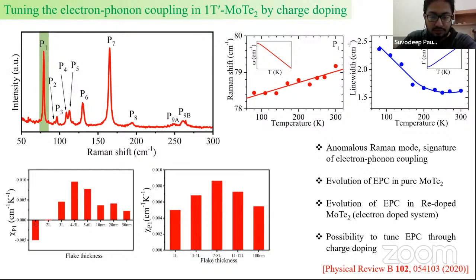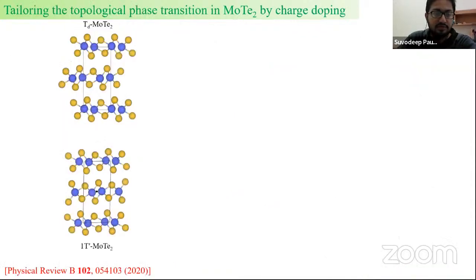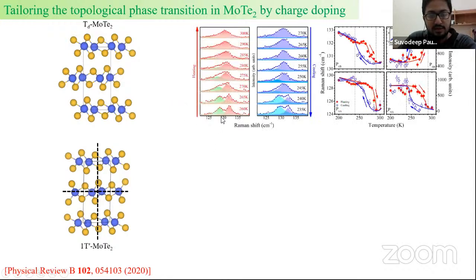So we went on to see the effect of this charge doping on the topological phase transition as well. Basically the Td MoTe2 and the 1T prime MoTe2 are the two topological phases, this being Weyl semimetallic and this being quantum spin Hall, as we discussed in our first slide. And as we also discussed, the 1T prime MoTe2 has an inversion symmetry, which is broken in the Td phase. And this breaking of inversion symmetry is manifested by the appearance of a new mode in the Td phase, which is not seen in the 1T prime phase.